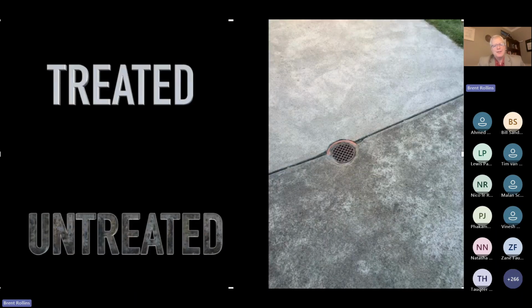The other thing that can happen with colloidal silica and sustainability is just the resistance to the natural environment. The concrete you see here is at a university in the U.S. The top concrete was placed 3 years before the concrete at the bottom. The difference is the top concrete was treated with colloidal silica to close that void structure. And you can see that it didn't have all the little capillary void structures for all the nasty biogenic material to grow.